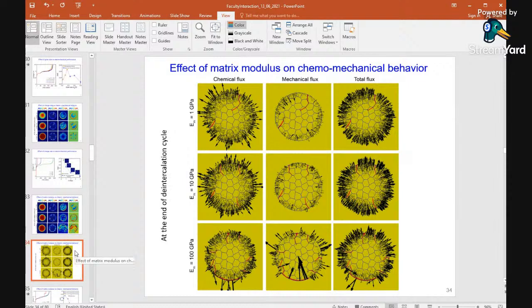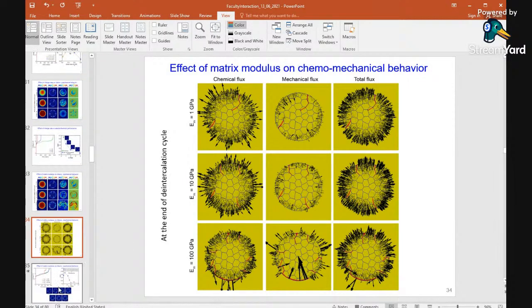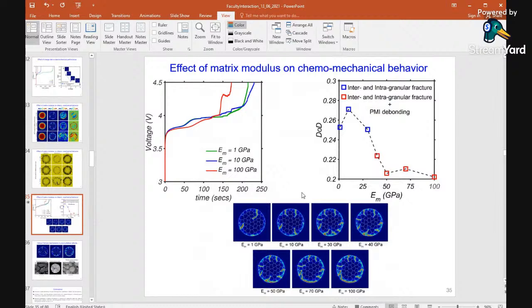So obviously a huge effect will come, which we can anticipate in the voltage curve. And that is exactly what we see. If we have a 100 GPa Young's modulus, the voltage drops and reaches the terminal voltage faster, because it depletes in other regions and deintercalates, reaching the terminal voltage in a faster way. So we have investigated all the possible matrix moduli, spanning an order of magnitude difference, 1 GPa to 100 GPa, and we can completely map how the depth of discharge will change with respect to the Young's modulus of the solid binder.